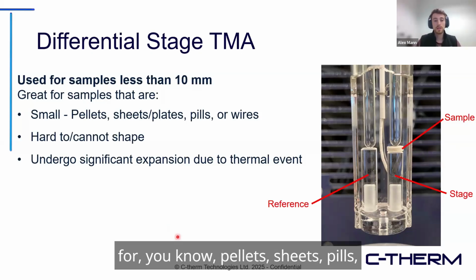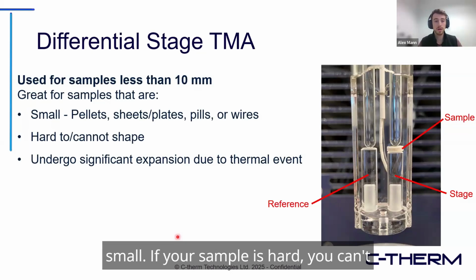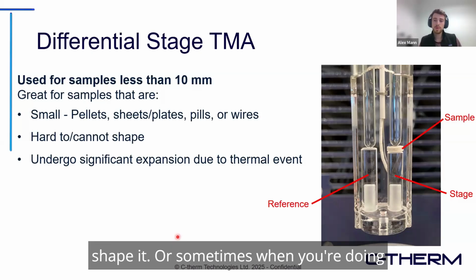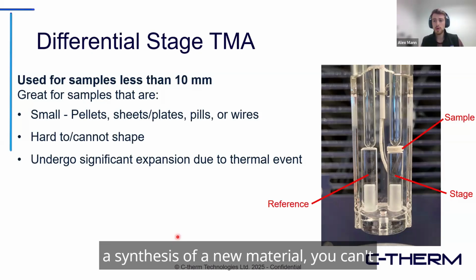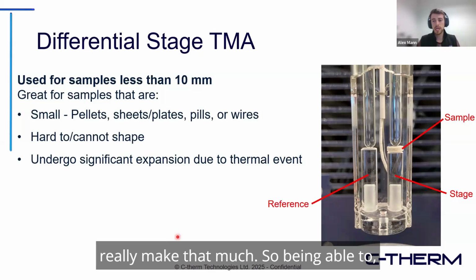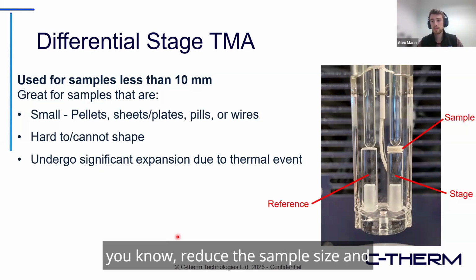So this is great for pellets, sheets, pills, wires, things that are just naturally small. If your sample is hard, you can't shape it, or sometimes when you're doing a synthesis of a new material, you can't really make that much. So being able to reduce the sample size and measure these small samples is very helpful.